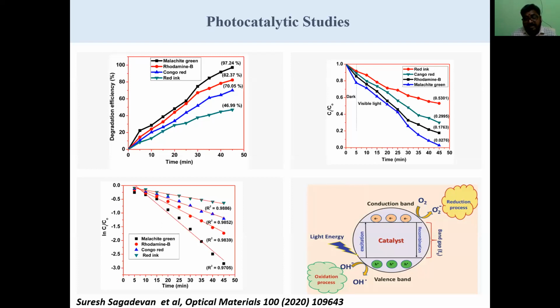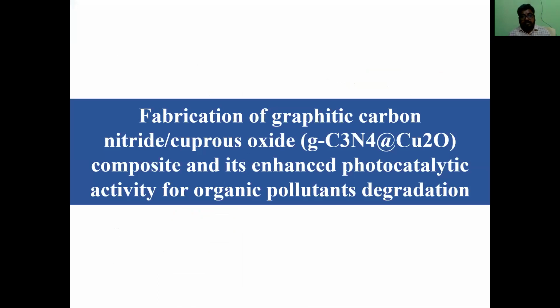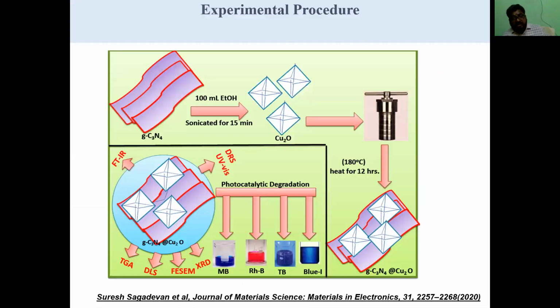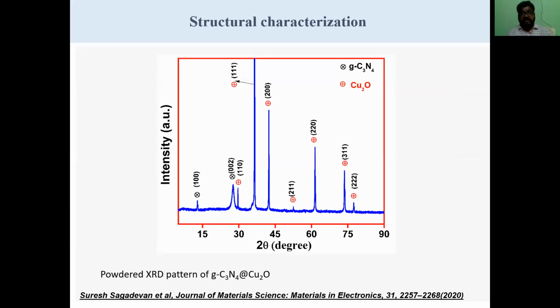For the observation of such photocatalytic activity under UV light, we hypothesize that some of the electrons in the conduction band of the composite are readily captured by the adsorbed O2, generating superoxide radicals. So next, I am going to present the fabrication of graphitic carbon nitride cuprous oxide composite and its enhanced photocatalytic activity for organic pollutants degradation. You can see here the experimental setup. We prepared the composite by hydrothermal method.